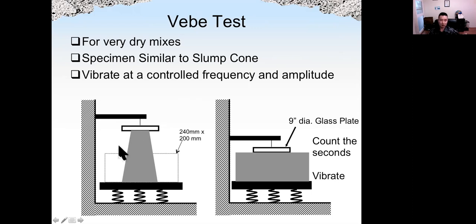And then the concrete is within a certain container with this size. Also, we have a 9-inch diameter glass plate. So when we vibrate the table, the glass plate will push the concrete into that container, and we count how many seconds for the glass plate to compact the concrete into that container. So this is for very stiff concrete mix, and we use the Vebe test instead.